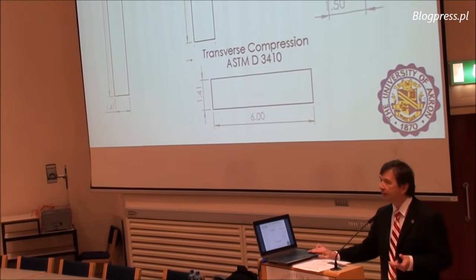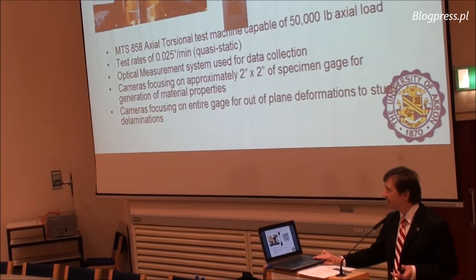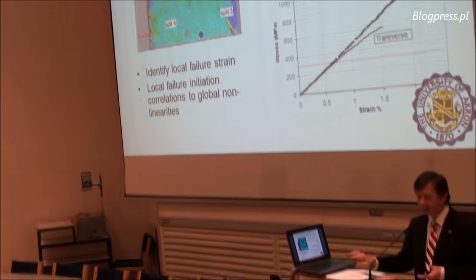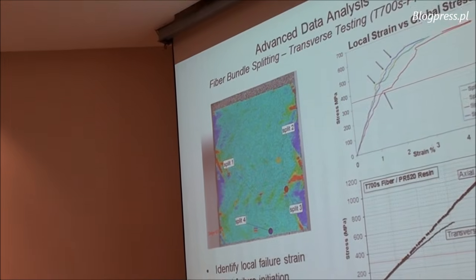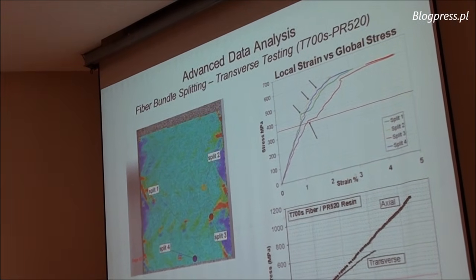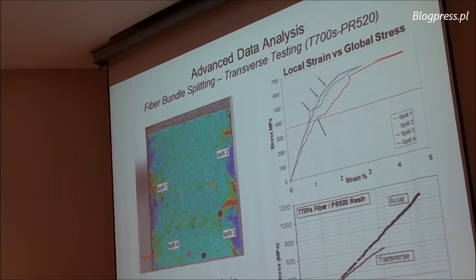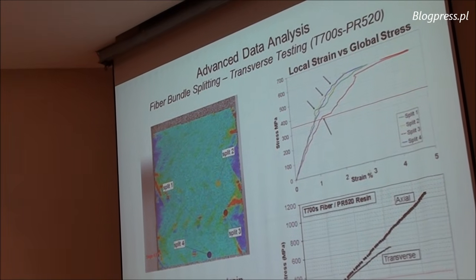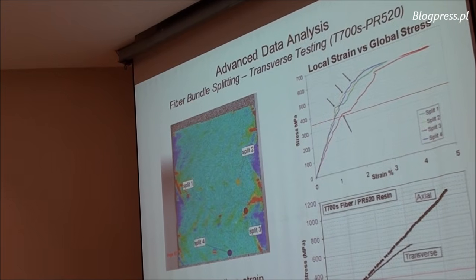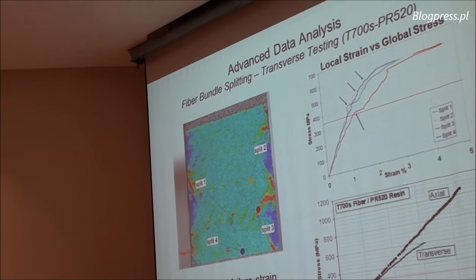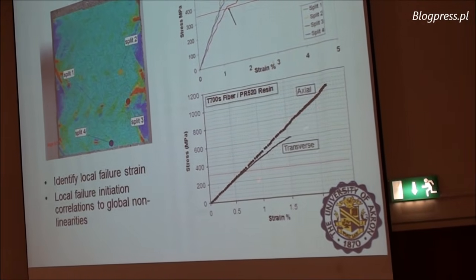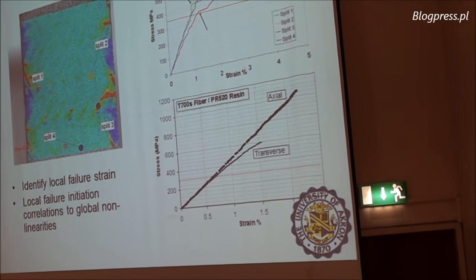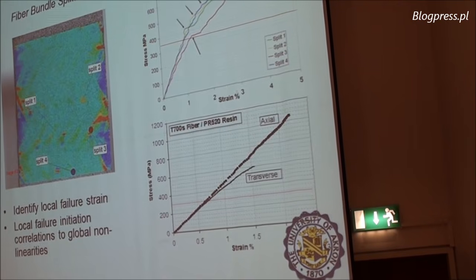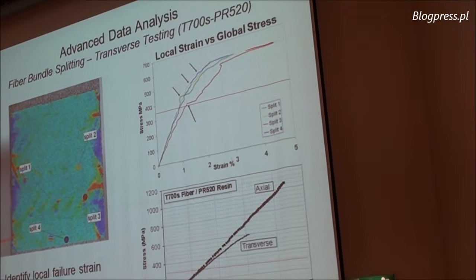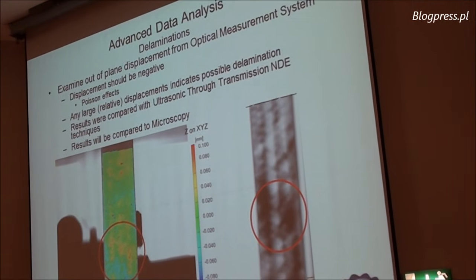So we had to develop a new test outside of the ASTM standard, and we were looking first of all to understand the so-called edge effect, and you can see this edge effect with the DIC methodology. This is an experiment where you can see the edge effect, which gives different stresses than inside. And of course, non-homogeneous stresses or strains are visible, like you can see maybe a damage, local damage, split or fracture or debonding between fiber and matrix. All of that can be overlapped on the global strain, but locally they produce a different stress-strain relationship, and they need to be known and somehow incorporated into the constitutive equation later in the modeling.